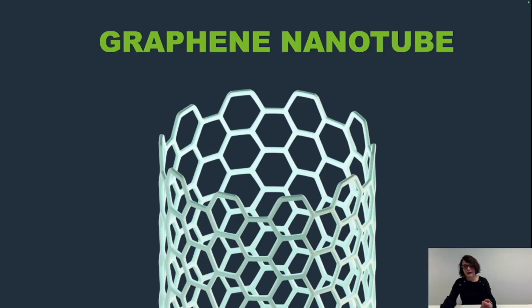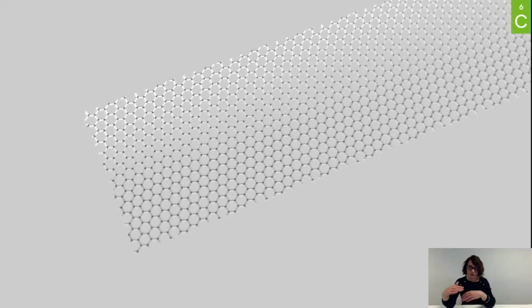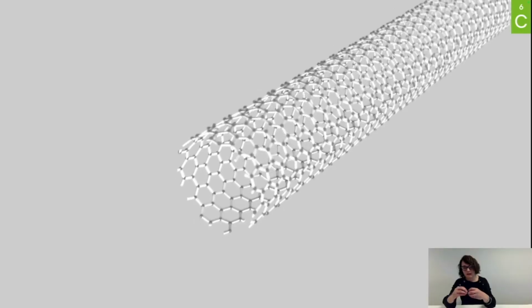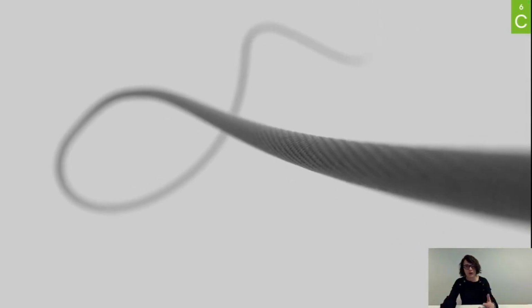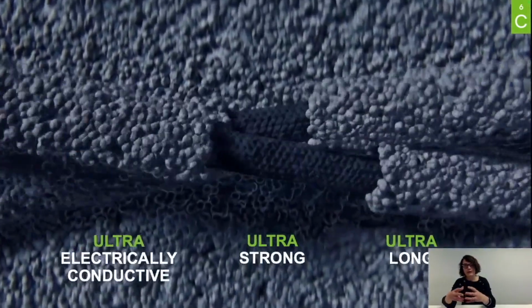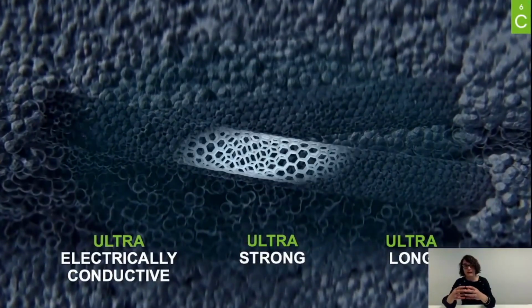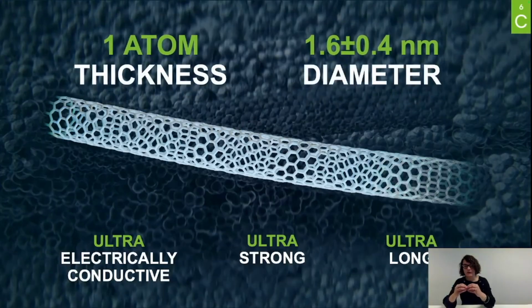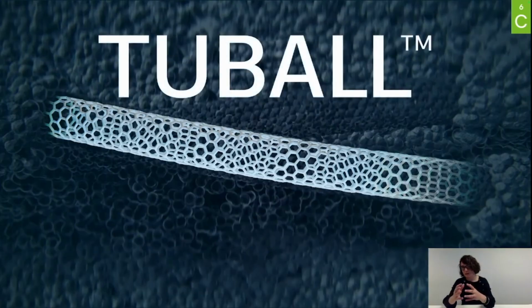Basically, these are the 3D dimension of a single graphene sheet, which rolled on itself in one single layer, creates very long and very thin particles, a bit spaghetti-shaped, as you can see on this 3D rendering. When we speak about very thin, think about a wall thickness of one atom and a diameter of approximately 1.6 nanometers. In length, they are super long. They reach 5 to 15 microns. And because these are carbon-based, they will be super strong and obviously very conductive electrically.